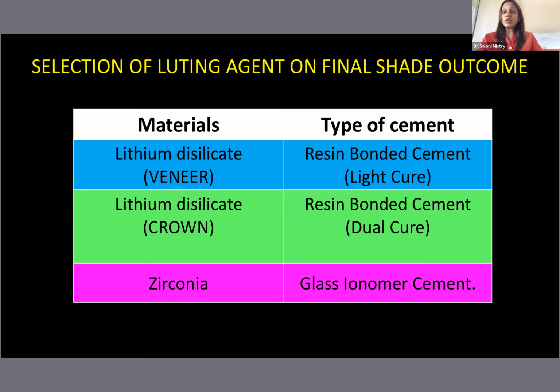With zirconia, obviously it's glass ionomer, or preferably resin modified glass ionomers can also be used, because those resin modified glass ionomers have better adaptability, better strength, and ease of manipulation, and that's why it is better to use. However, nowadays with the newer kinds of zirconias which are coming, again, as I said, if you want to use a dual cure resin cement, you have to have a tribochemical silica coating, which is like an air abrasion. It is by Rocatec Plus. You can read more about it.